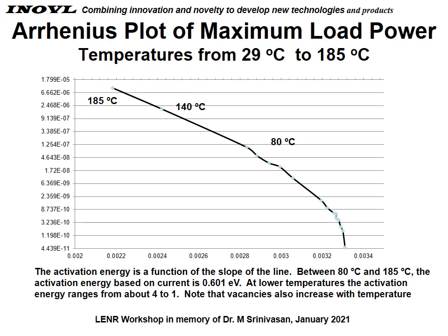The activation energy is a function of the slope of this line, and if you calculate the activation energy between 80 degrees C and 185 degrees C, it was about 0.601 electron volts based on the current. At lower temperatures, the activation energy ranges from about 4 to 1, and the vacancies also increase with temperature. This is one of the reasons we think that vacancies are important.